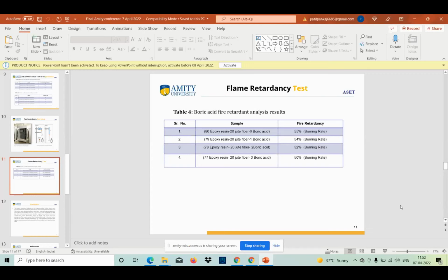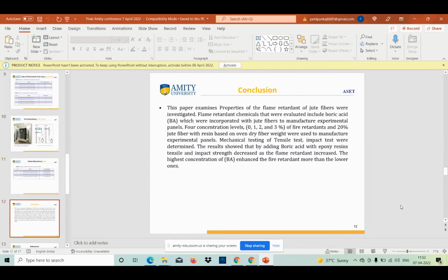So using these tests we will categorize the results. We conclude that we used four concentration levels, that is 0, 1, 2, and 3% of the fire retardant, and 20% jute fibers with resin base, over oven dry fiber weight, to manufacture the experimental panels. Then the mechanical tests were carried out.